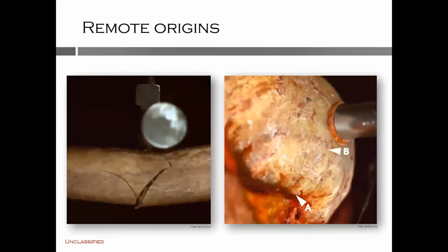Fractures don't always initiate in the immediate region of impact. They certainly can, but impacts impose stress distributions such that fractures can initiate in areas elsewhere on the structure. Bending forces, for example, can cause a crack to originate in a location remote from the impact site. This has been documented in numerous studies, including those involving bone.